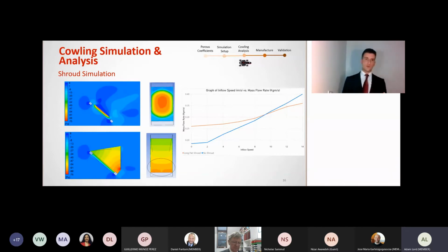The mass flow rate was obtained using Fluent by finding the surface integral for mass flow rate at the radiator interface. And as expected, the mass flow rate with the cowling is significantly more than without. However, as you can see, this effect is most notable at lower speeds, and beyond a certain speed, not only do the mass flow rates level out, but at higher speeds the shroud actually begins to act as a blockage and does have a negative effect on the mass flow rate. But having said this, it is at these speeds that cooling is most critical.